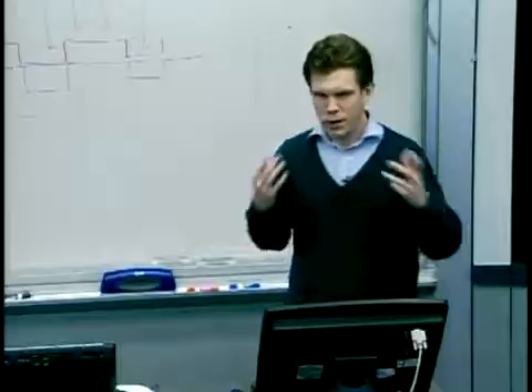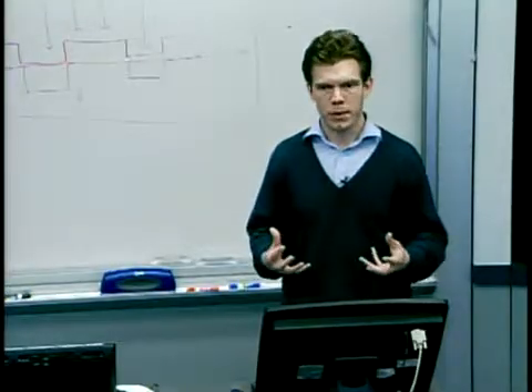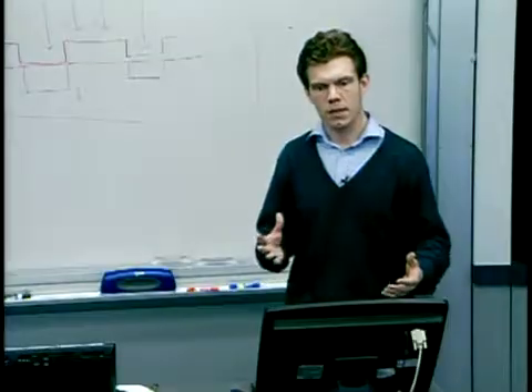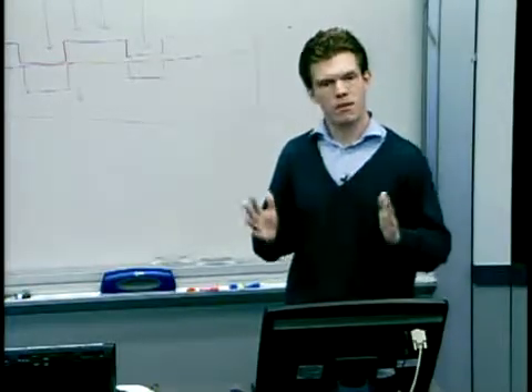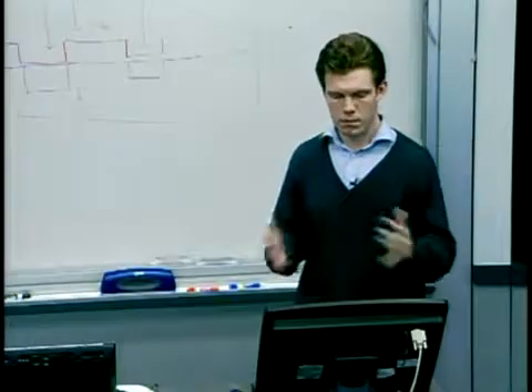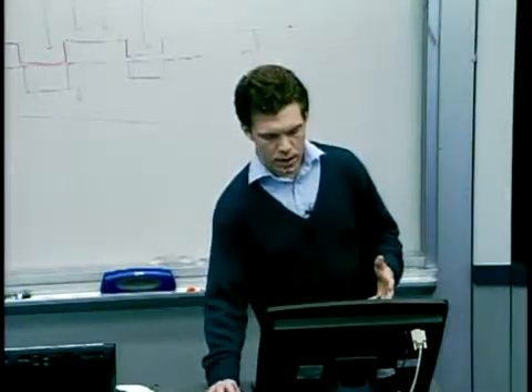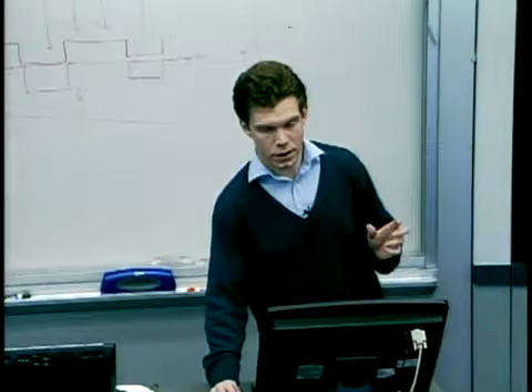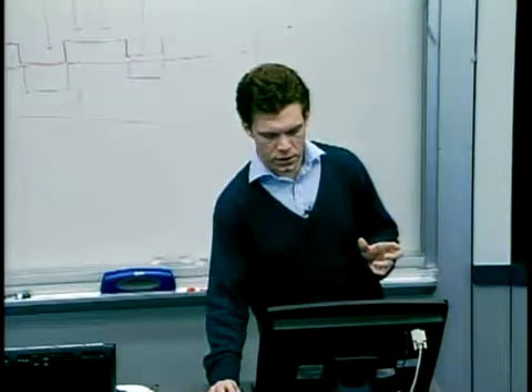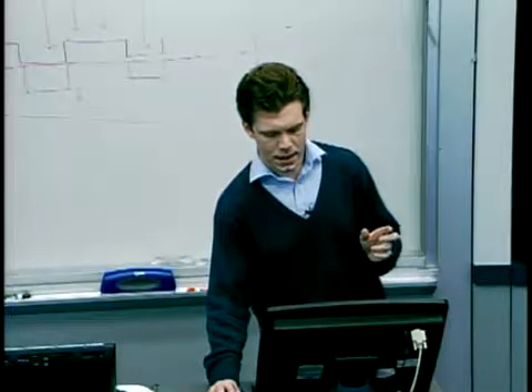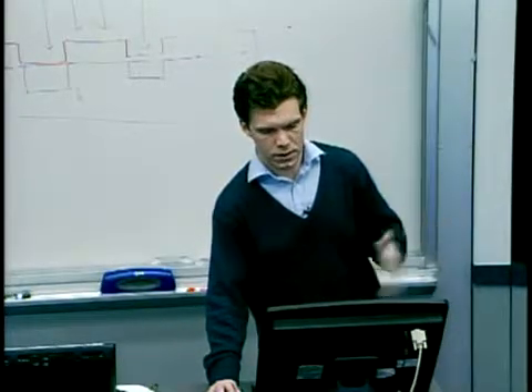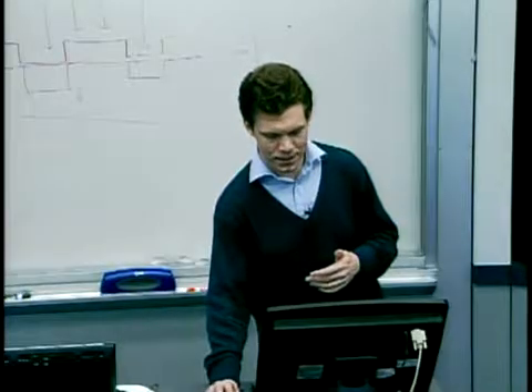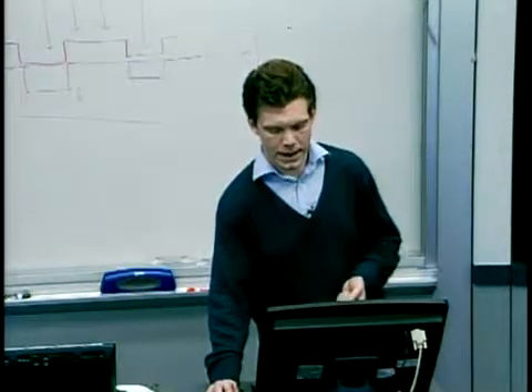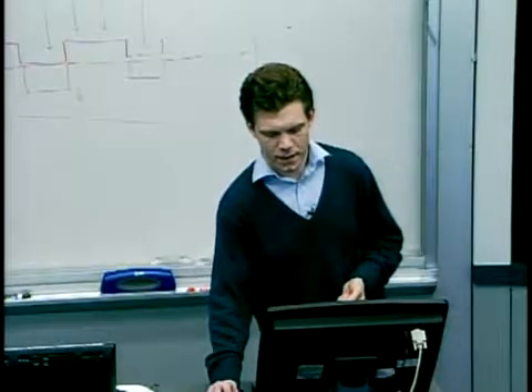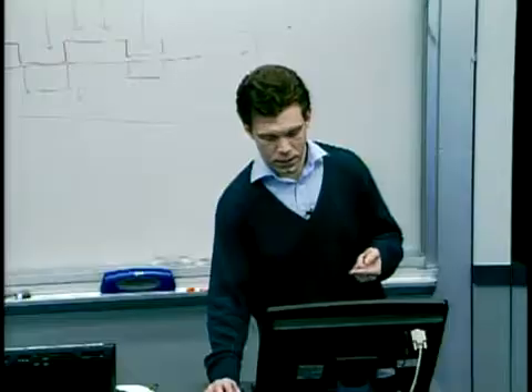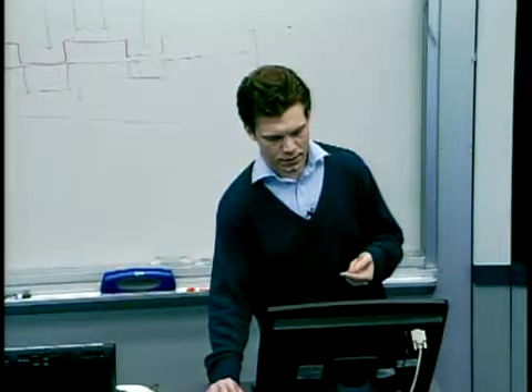But we're talking about computing approximate topographies, and this is going to be done in a discretized way, where we split the surface of the polymer into a series of square elements, so we can translate this point load response into the response of the surface to unit pressure applied over one element of our discretized surface. So this is the plane of the surface of the wafer, the surface of the polymer. And we're trying to express how far that part of the surface goes down when you apply unit pressure here. And that's the answer.